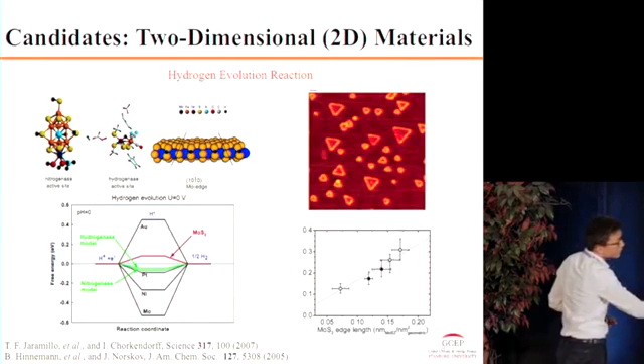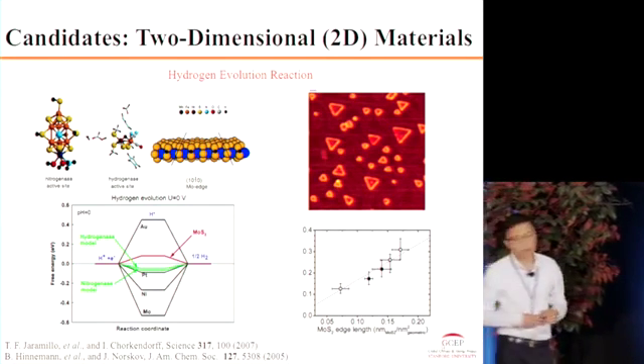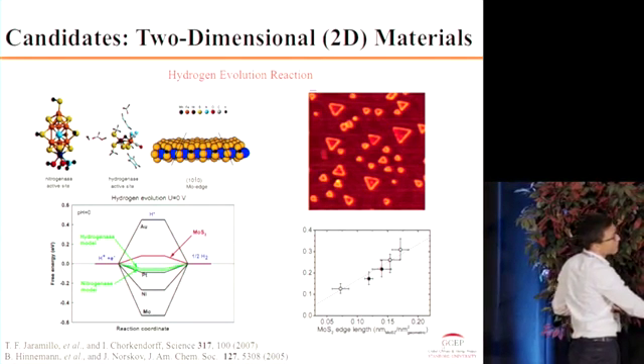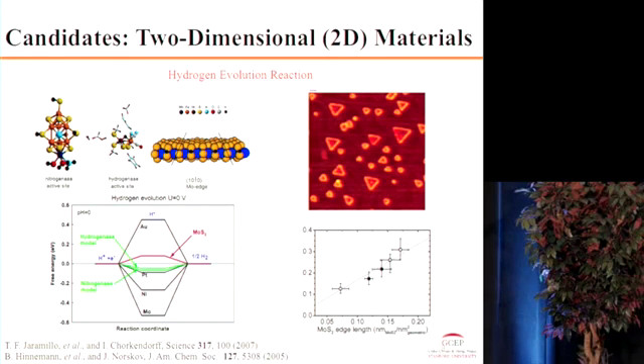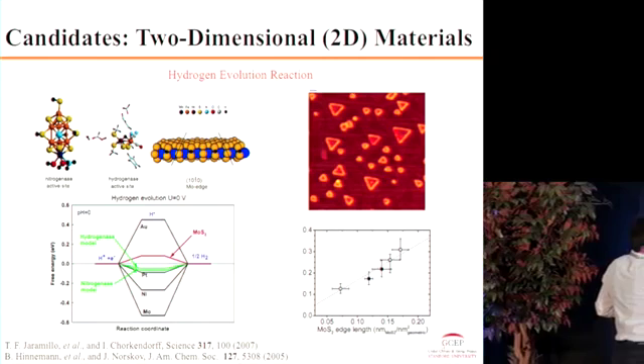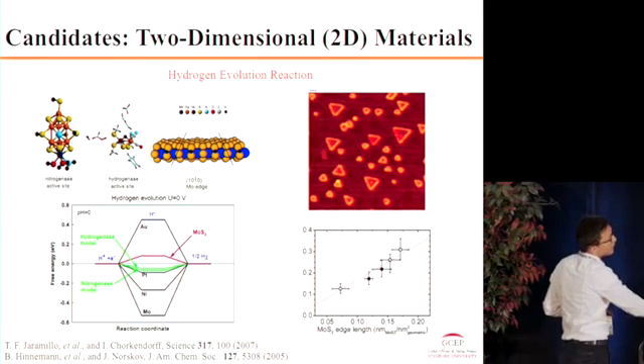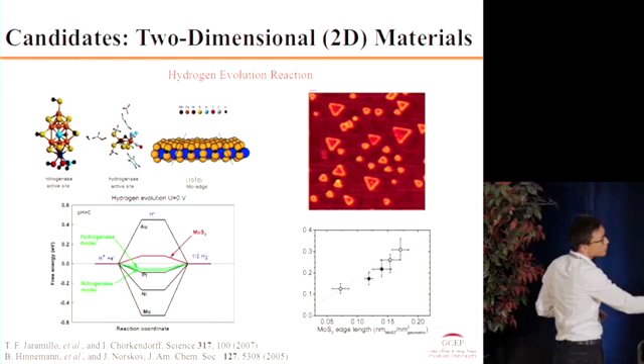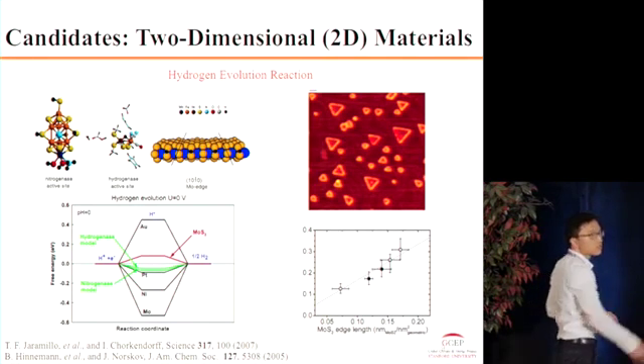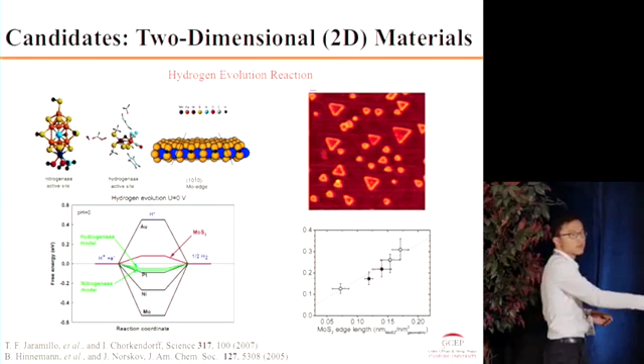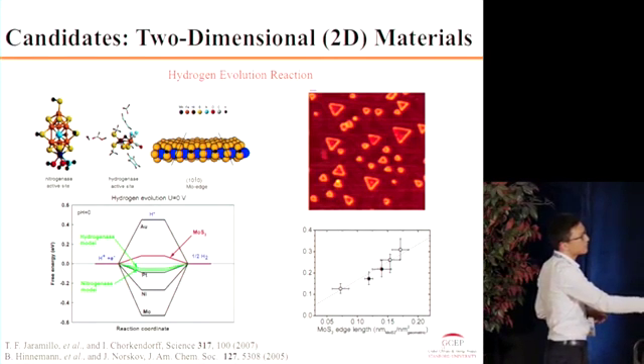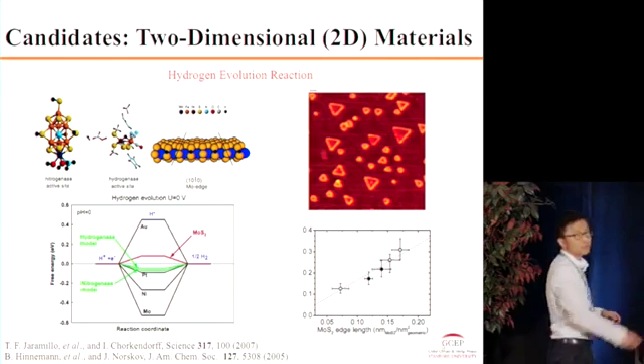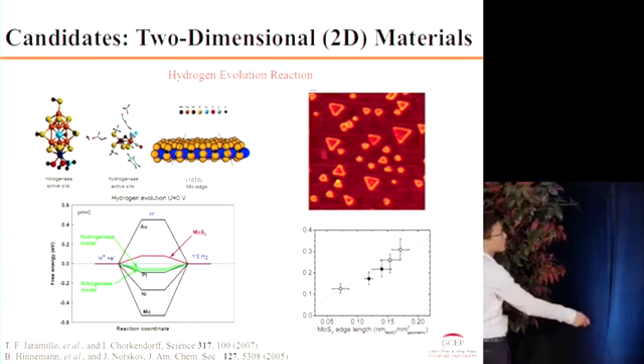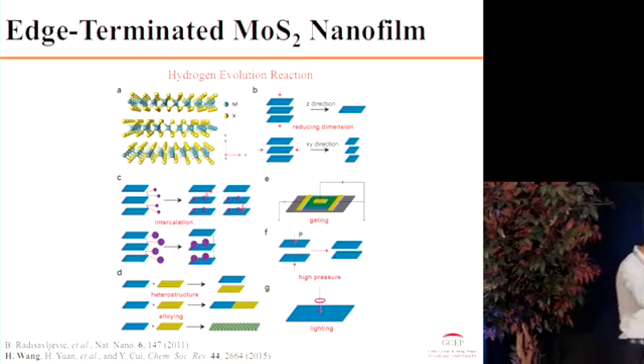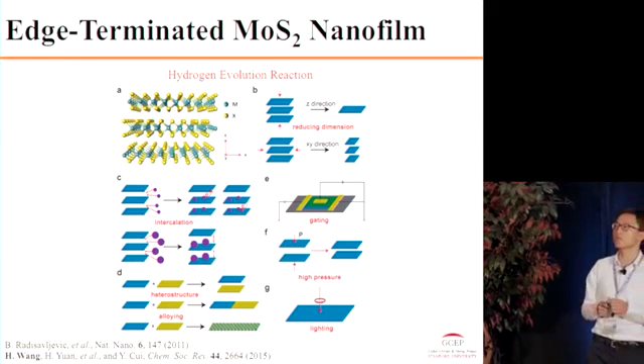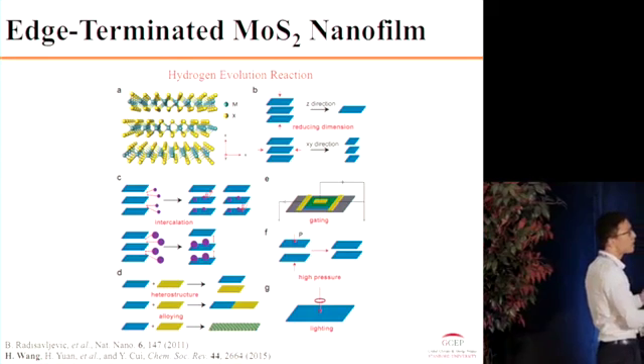And Professor Tom Jaramillo, when he was a postdoc, developed this experimental demonstration of the active edge side, where he grew molybdenum disulfide nanoplates and tested the catalytic activity. This activity has a linear scale with the length of the edge, but not with the surface area of the plates, which strongly demonstrates that it is the edge side that plays the key role in the hydrogen evolution reaction. So we think about the atomic structure of molybdenum disulfide and what is the best structure for us to do.